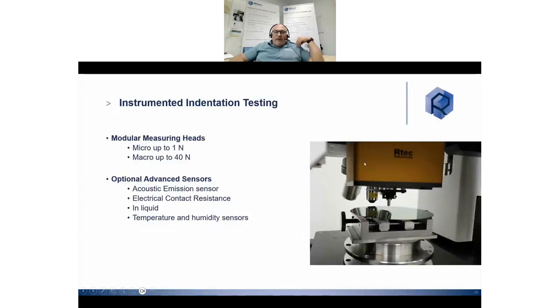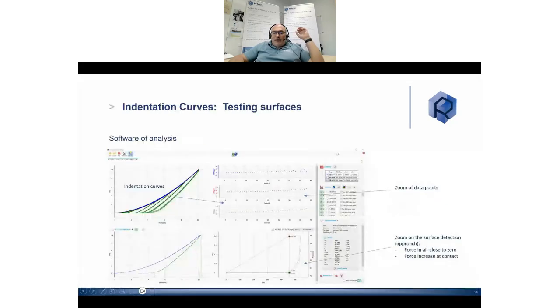And to finish, the last possibility is to directly combine with an indentation head, micro or macro. You see here we fix a Berkovich or Vickers indenter, and directly after the test we are able to measure the hardness, HIT, and the standard elastic modulus, EIT. And finally, you see here the superposition of the curves we analyze, the contact point, and the statistics between indents and the values we have.